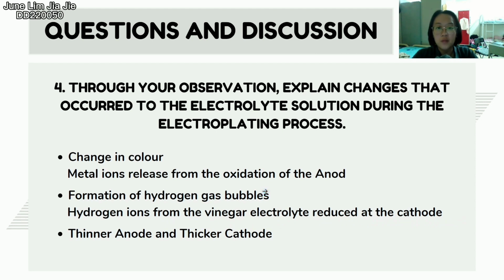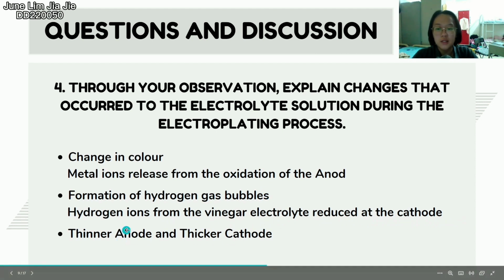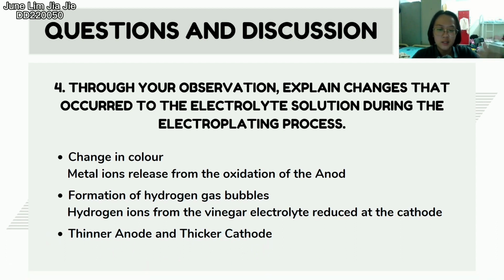And the last observation we can notice from our experiment is that, over time, the anode becomes thinner and the cathode becomes thicker. This observation holds true for setup 1 and setup 2, but for setup 3, because the aluminum 3+ ion was unable to reduce at the cathode, there is no thicker cathode in our setup 3.